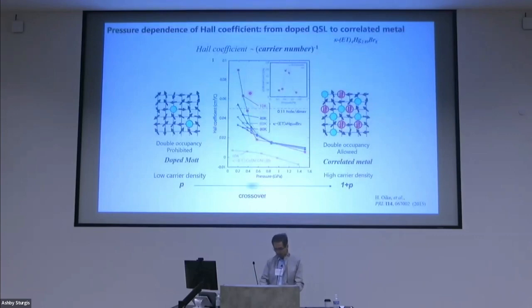Okay. And this is the pressure dependence of the Hall coefficient. Please take a look at the low temperature data, for example. The Hall coefficient is large, and then this is suddenly suppressed just around 0.5 GPa, and then it is flat and levels off. So this means that in the low pressure region, the carrier density is very small. So low carrier density here, but high pressures are high carrier density conductors. And we think that this is the range where the double occupancies are prohibited with the very high Mottness. And so the carriers are the doped carriers.